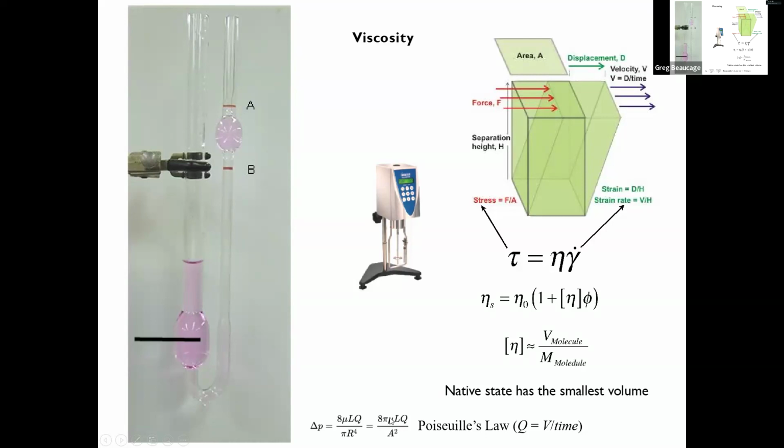Just like here, viscosity is the only thing that doesn't change. So the time that it takes to go through this is proportional to the inverse of the viscosity, like 1 over the viscosity. Longer time would be higher viscosity with that one. And the rest of the numbers are constant. So this works pretty good. And when you want to get a lower concentration, you just add more solvent. So you'd start it filled up to here. And you get 4 or 5 concentrations by just dumping more solvent in and kind of letting it shake for a little bit, then run it again.